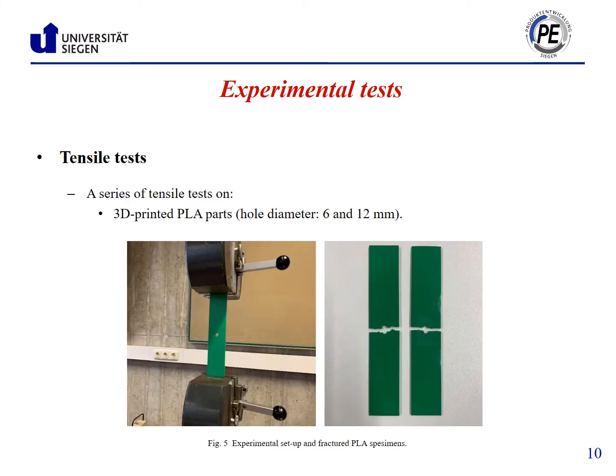In this study, a series of tensile tests was carried out under displacement control via constant crosshead movement until failure. Indeed, a hydraulic machine was used to conduct the test under a static loading condition. In this slide, you can see a 3D printed open hole plate specimen under tensile test conditions and fractured specimens on the right side. Regarding the ASTM standard, failures that occur at the hole are acceptable failure modes. In our study, all specimens showed a failure at the hole, which confirmed their results are acceptable.